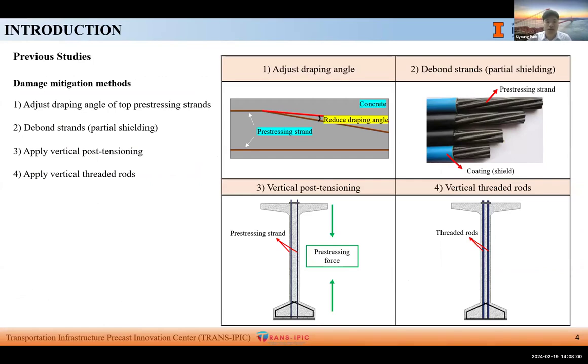Several studies were conducted to mitigate the end region cracking. The following 4 methods were developed as solutions. First is to adjust the draping angle, and second is debonding strands with partial shielding, such as an unbonded strand. Both methods showed some effect on the end region, with up to 20% less damage, but there was a reduction in shear capacity when conducting 2-point load experiments.